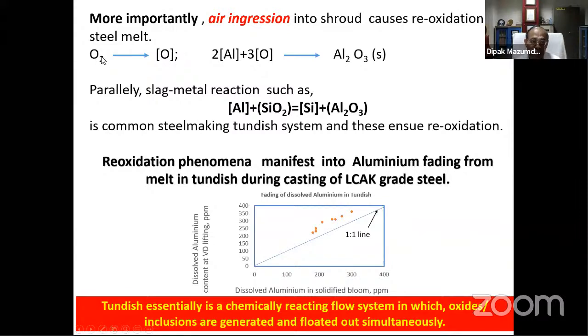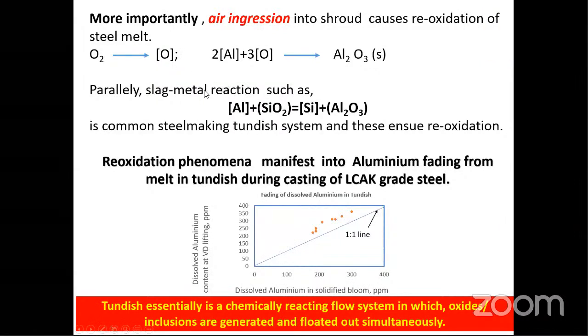And this dissolution is driven by a concentration gradient, because the atmosphere contains a partial pressure of oxygen of 0.21 atmosphere. And steel could be containing 10 ppm, 15 ppm oxygen depending on the extent of deoxidation. And the dissolved oxygen, when it exceeds a critical value, particularly in aluminum steel, it can react with aluminum to form alumina. And this is a solid product. And this solid product acts as an inclusion unless they are all removed.